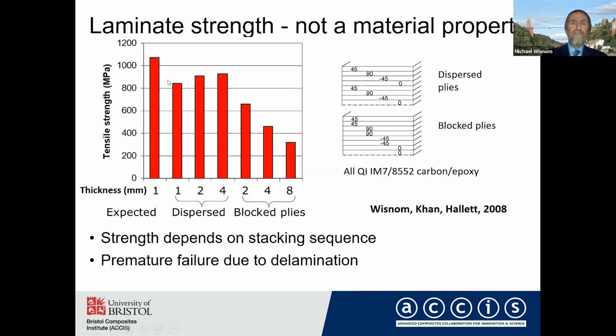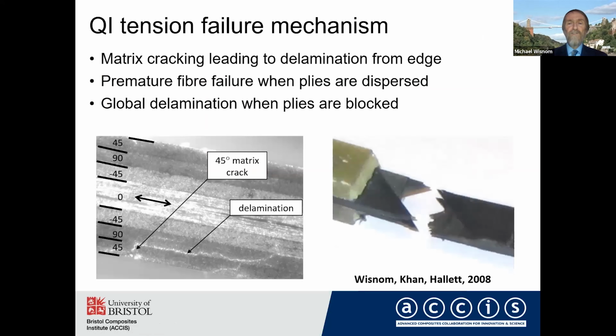So we have these first three here are dispersed plies, where we repeat the sublaminate through the thickness. And these ones here are block plies, where we block up the plies of the different orientations together. And you can see there's a large difference in the tensile strengths of these different laminates. And the reason for this is because we're getting premature failure due to delamination. If we look at the failure mechanism, what happens is we get matrix cracking, particularly in that surface 45-degree ply, and that leads to delamination from the edge.